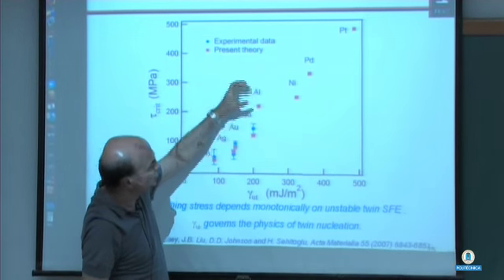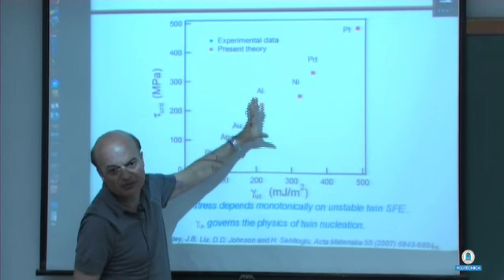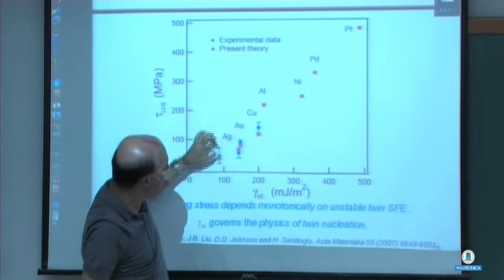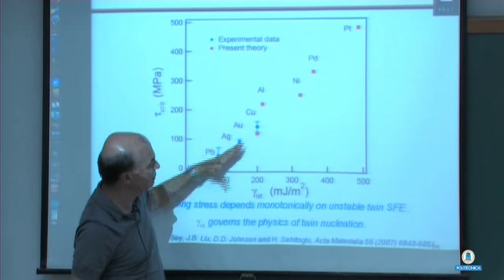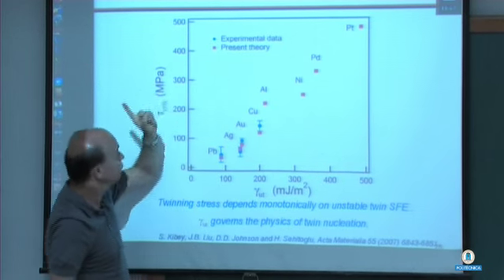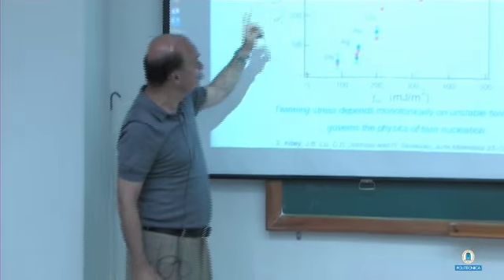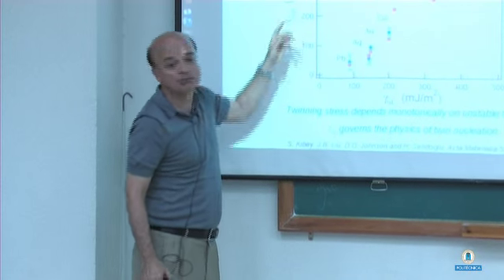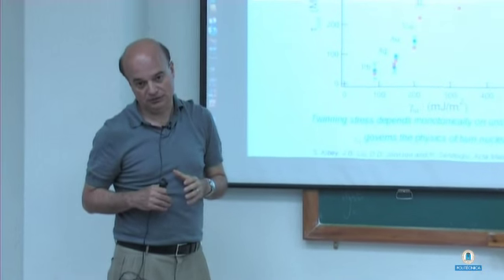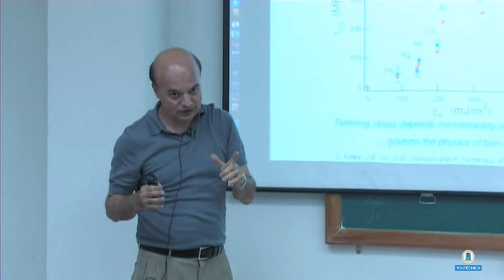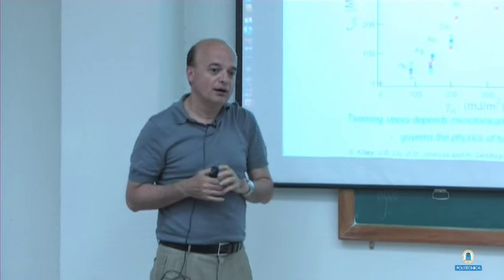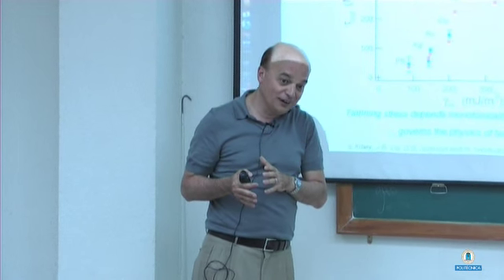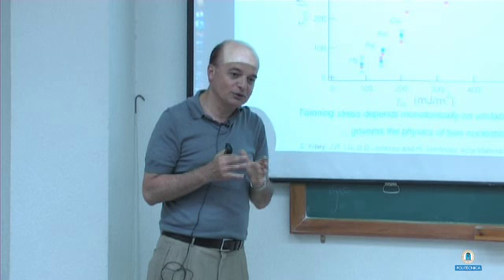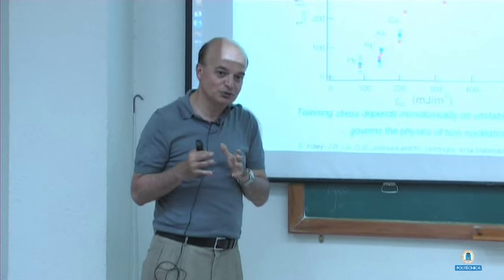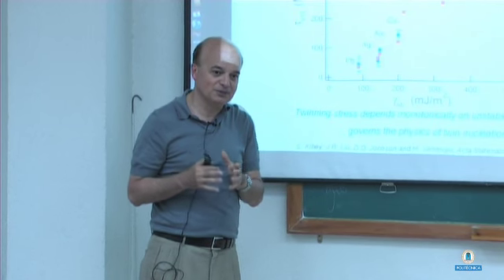Now, you could find some twinning stress results for aluminum these days. You can't put it here, but we looked at the old literature and primarily looked at our prediction. And the most important thing, perhaps, is that these numbers are of the order of megapascals, not gigapascals. So you need to invoke continuum theory along with atomistic theory to be able to predict realistic values of applied stress, twinning stress.